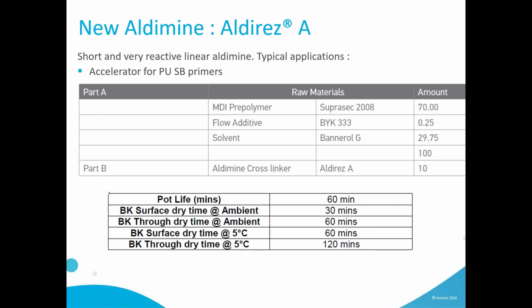And as you can see in this formulation, it can be used with PU primer to achieve very fast drying. You can even get to 2 hours full drying, even at 5 degrees. As an example, the system won't even cure at 5 degrees without any Aldirez A.